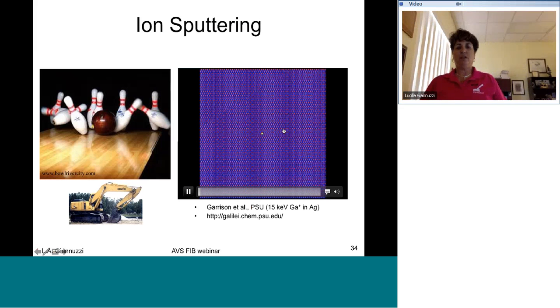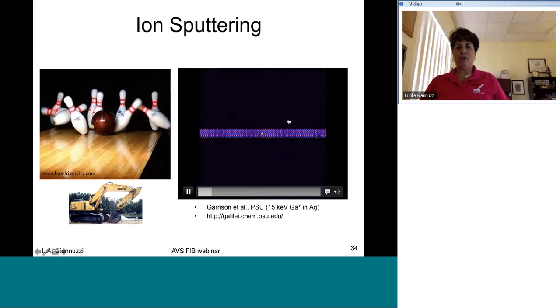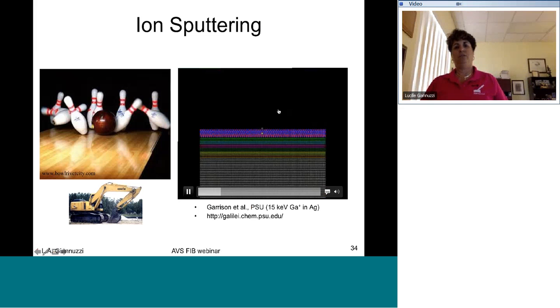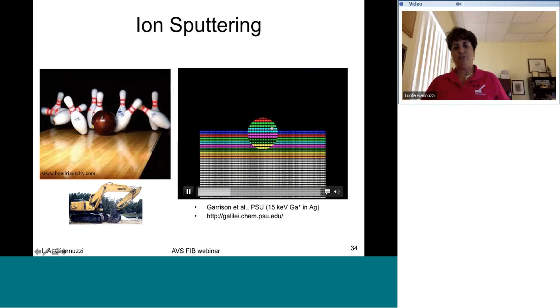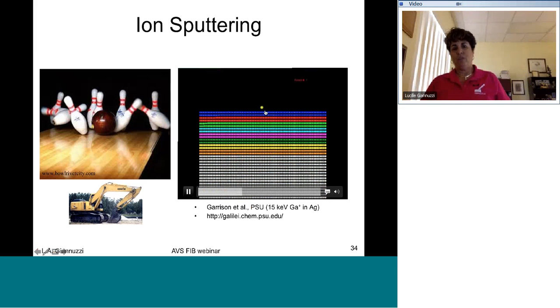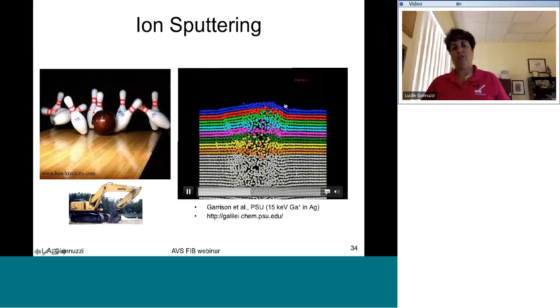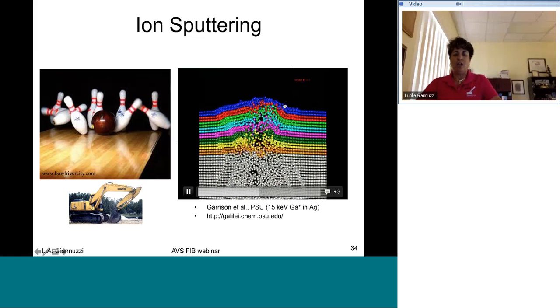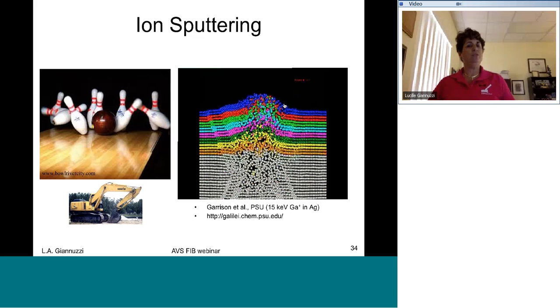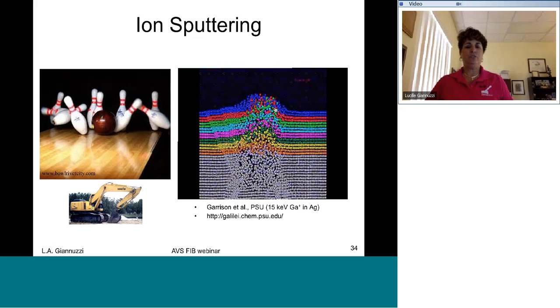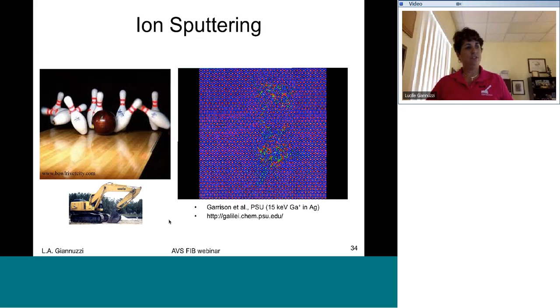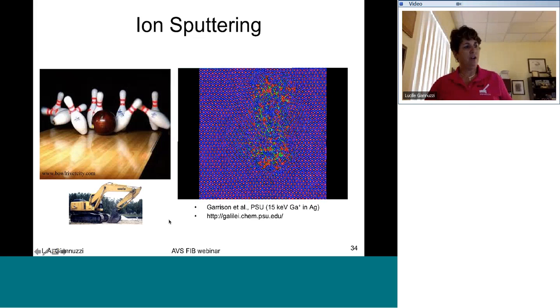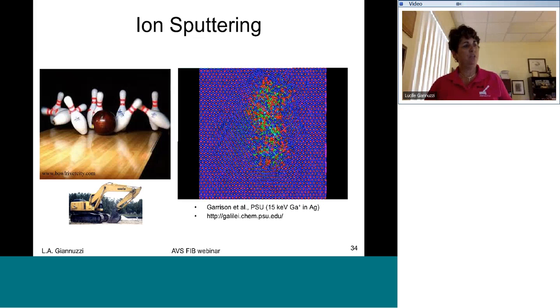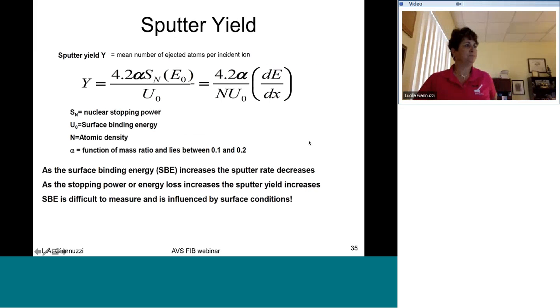One is because the recoils come from a distance that can be several nanometers away from the incoming ion. And two, of course, with that same 2 nanometer beam in different materials, just because the ion-solid interactions are going to be different, you're not going to be able to mill the same type of hole in different materials. Okay, so the sputter yield is the mean number of ejected atoms per incident ion.